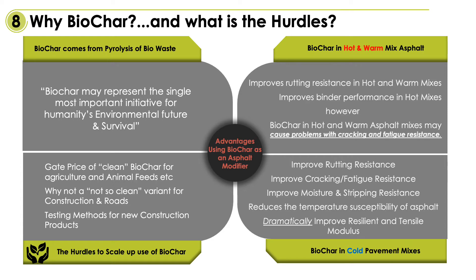Combining biochar with our special anionic emulsions and creating a different type of bonding mechanism, we see far superior performance properties with our cold premixes. With improved resilient and tensile modulus properties, we can actually use less than half the amount of material compared to hot premix for a same-duty road installation. We can therefore include higher priced raw materials and still be competitive, making biochar use in our road products the norm.